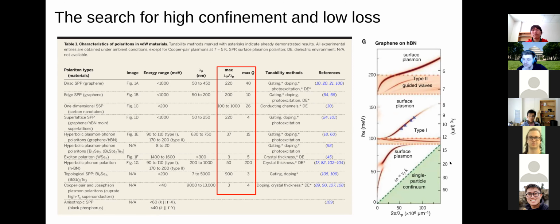And something cool about this is that, with something like graphene, you can electrically gate it to tune it. And so people are very interested in these materials broadly as platforms which can be used to create dispersion relations which can be tuned dynamically, potentially in place by electrical gating. And this sub-wavelength, highly confined nature is something that's going to be important later on in the talk. So maybe just keep that in mind.